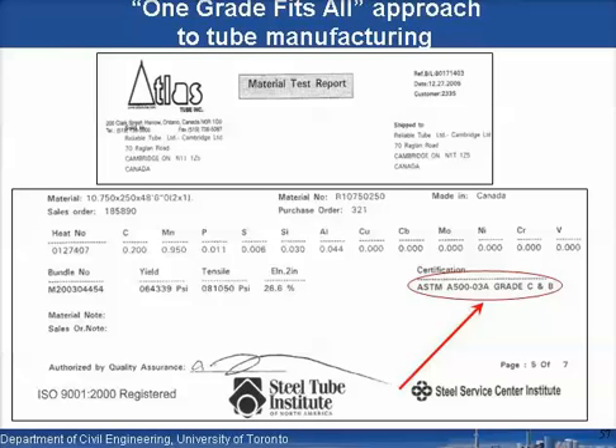Well, if we go to the AISC seismic spec in 2005, this particular table, and take out the RY and RT factors, we can see that they're different for different types of products. But they're the same for ASTM A500 grades B and C, interestingly enough, and we have an RY of 1.4 in this particular case. ASTM A501, which is a hot form product, is now back in the market again. And it's also assumed that we have the same RY value for that at the moment, but these are in great debate in technical committees. RT represents how much the ultimate strength is likely to overshoot, and these are again different values.